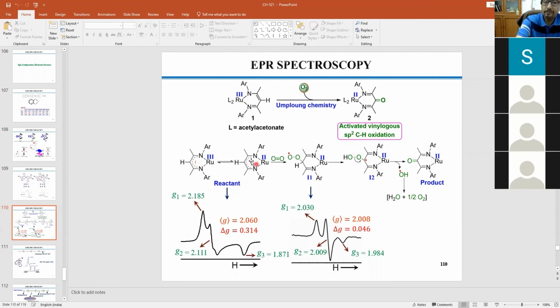So the total number of electrons remains fixed. Because of this radical composition on top of the metal, this is 80% or more and this is less, but the 20% resonating configuration cannot be neglected. So that is how it is considered as a resonating form, and if you look at the g and delta g, that is also reflected over here. And that again allows it to react with triplet oxygen and then you get the superoxide intermediate.